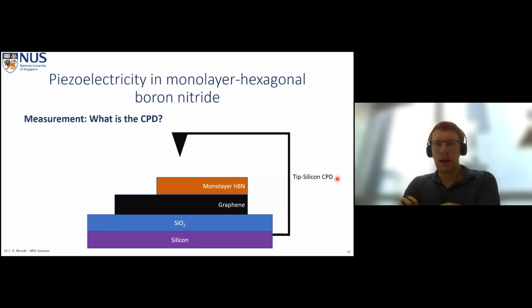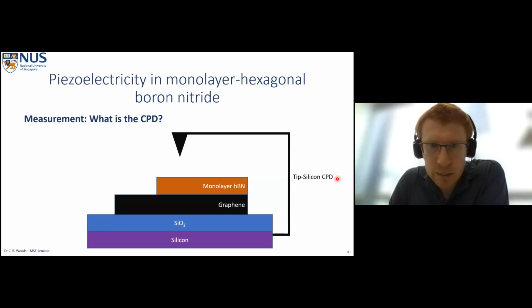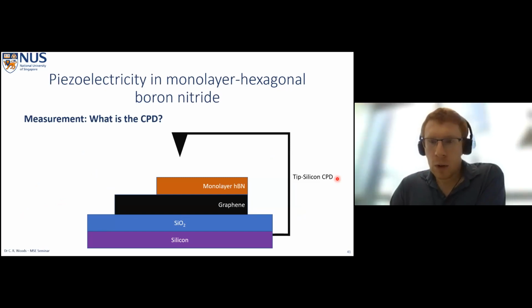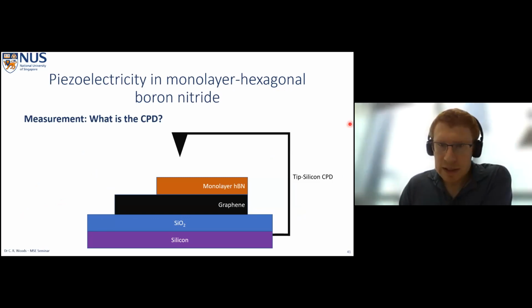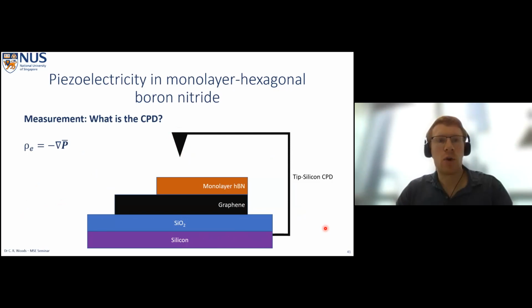So let's consider exactly what's going on in our sample for our measurement. A simplistic view is that we have a metallic tip connected to our silicon backgate. And we induce some charge due to a gradient of polarization in our monolayer boron nitride layer. So this is not just polarization, but a gradient, and this induces some charge, which we can put here. We say a positive charge here.